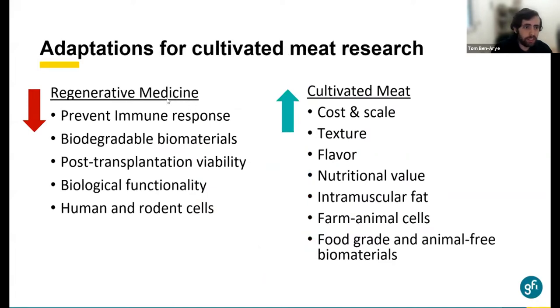In regenerative medicine, one of the key issues is prevention of immune response, because you are going to transplant the tissue inside the body, and many of the materials were optimized and developed so they will prevent immune response. And that's something that is irrelevant for cultivated meat. In addition, materials that degrade well after transplantation: in cultivated meat, the entire tissue goes into your stomach, and it will be degraded in a much easier manner compared to a tissue that is transplanted. However, you do need to consider the fact that in cultivated meat, you consume a much larger sample compared to regenerative medicine, where you usually don't use as large a tissue.